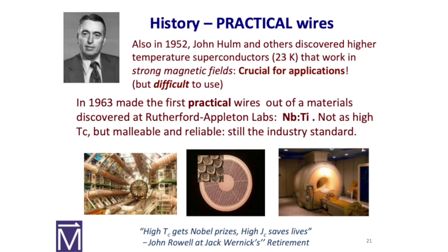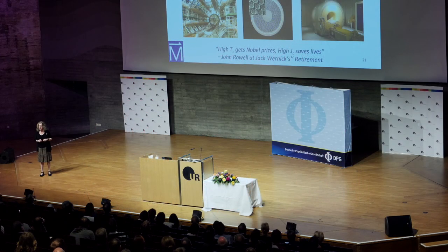Up until about the same time, John Hulm was at Westinghouse, and he discovered a material. It's a compound; they're called A15s. The one that's used in the field nowadays is niobium-3-tin, and it's got a much higher TC, and it's very, very strongly type 2, so it can maintain its superconductivity in high fields. And that was supposed to be for applications, but hold on there. This material is very difficult to use.